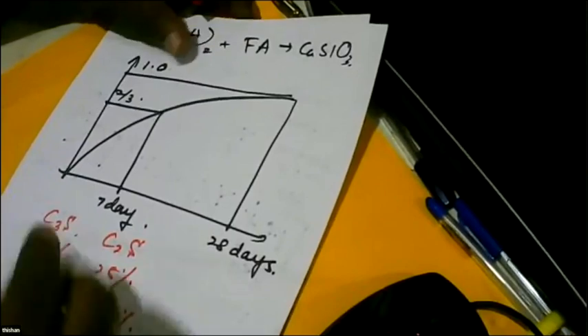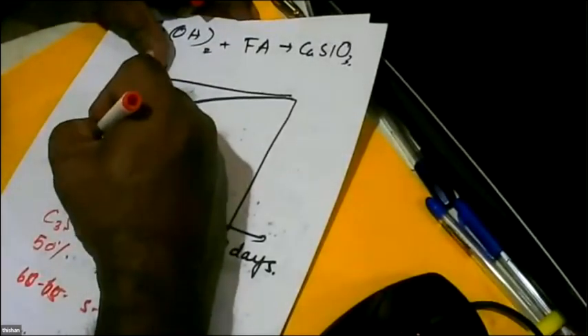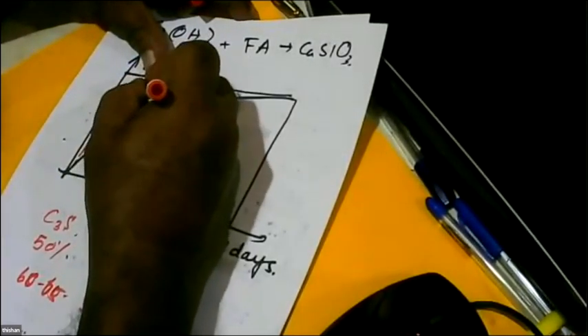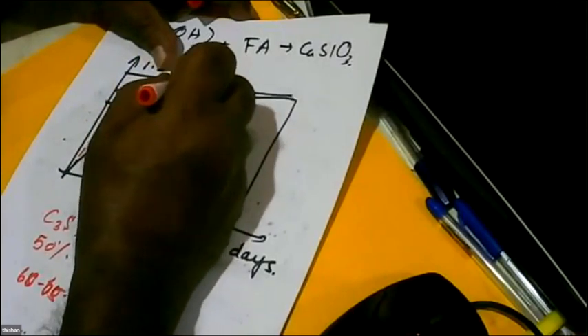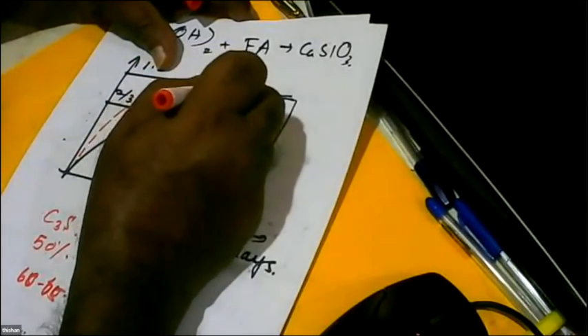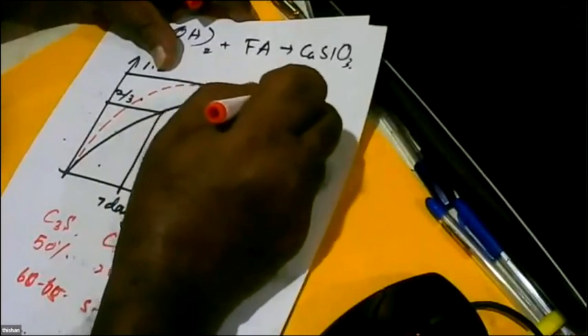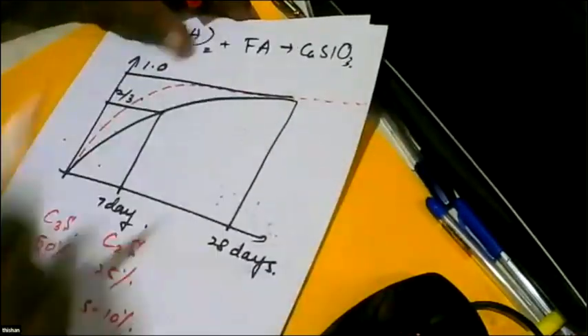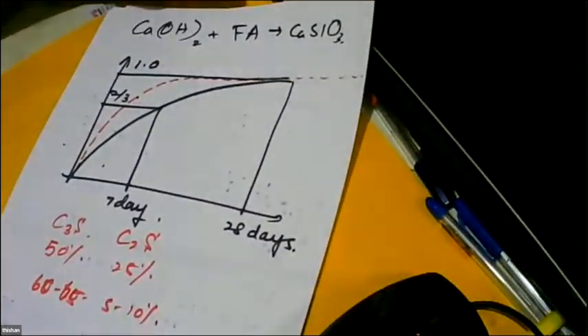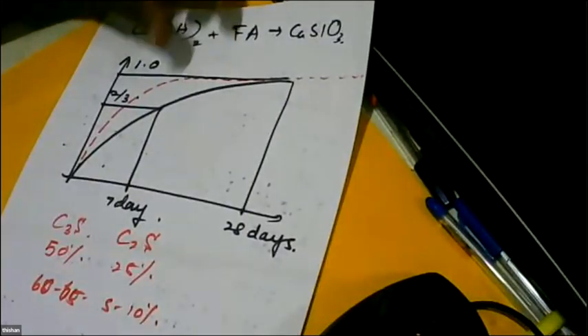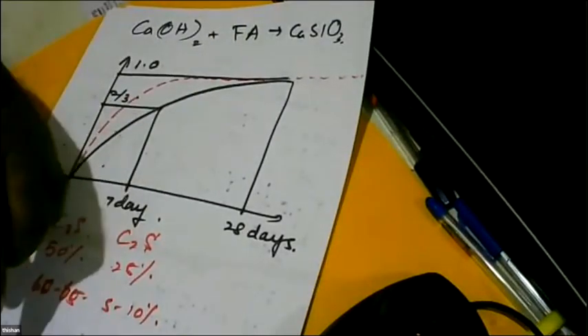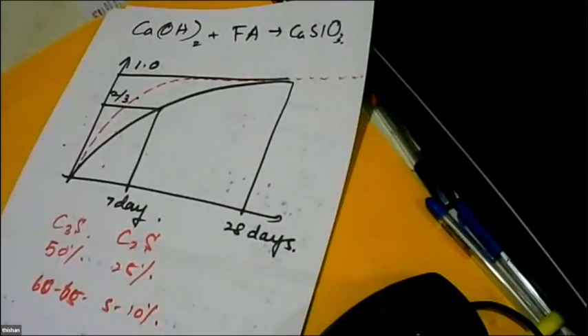What happens? Now the reaction goes in a different curve. It reaches 7 days strength of 28 days very fast, but it does not increase the strength very much. It goes in a curve like this. So that's why we say, if you can cure concrete for 7 days these days, it is sufficient. You don't have to cure it for 1 month.